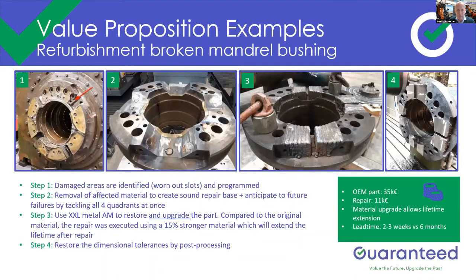Second example is this broken mandrel bushing that we refurbished. Again, you see on the top of the slide the different steps which are being taken. So we start from the original defect, we remove that defect, we fill it with new material, and we do the final machining to bring it back to the correct dimensional tolerances so that the part can be used again once it leaves our production line.